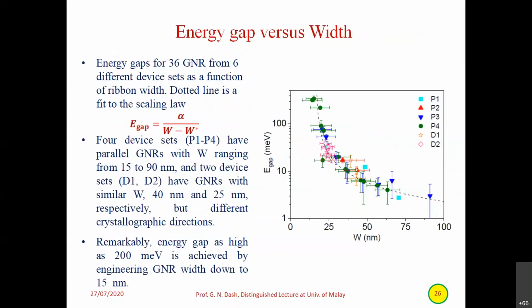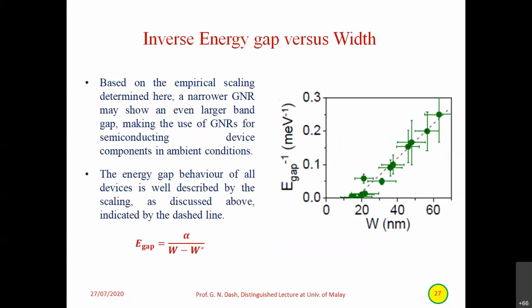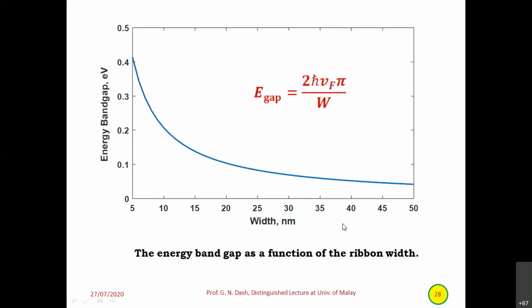This is width dependence again, what we have already studied. Some experimental studies by other groups have been depicted here, and you can see this is the curve which shows that E gap is equal to alpha by W minus W star. And remarkably, an energy gap as high as 200 milli-electron volt is achieved by engineering GNR down to 15 nanometer. Now, inverse energy gap versus width is a straight line, as you can see, because that is a curve, so it is 1 by W, therefore 1 by E gap against W. This is the theoretical graph of energy band gap versus width, plotted from the relation 2 h-bar v_F pi by W that we have already given.